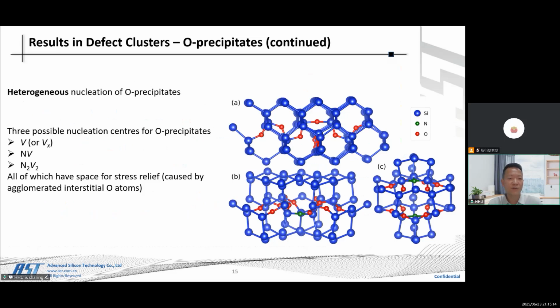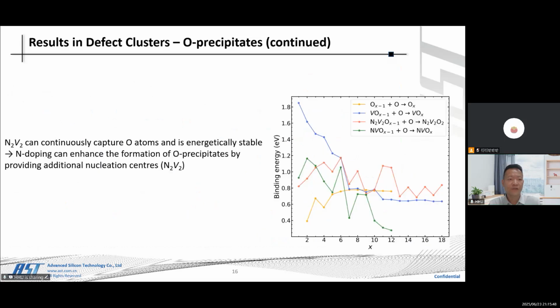Another kind of oxygen precipitate is based on the heterogeneous nucleation of oxygen precipitates. There are three possible nucleation centers for oxygen precipitates: V, NV, and N2V2, all of which have space for stress relief caused by the agglomerated interstitial oxygen atoms, as shown in figures A, B, and C. From the studies, we find that N2V2 can continuously capture oxygen atoms and is energetically stable. Nitrogen doping can enhance formation of oxygen precipitates by providing an additional nucleation center, N2V2.